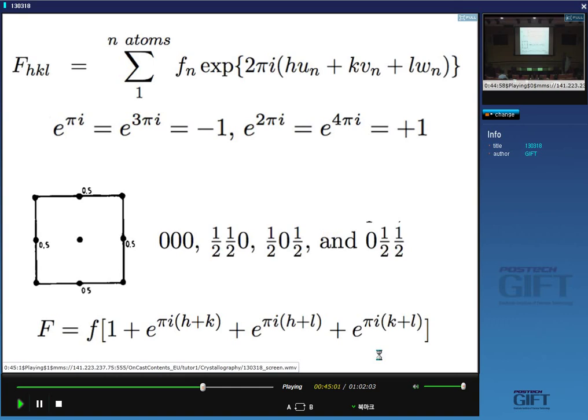So this is now the structure factor for our copper. And if I substitute any plane into this, then I will get whether we should get a reflection from that plane or not. So supposing I substitute HKL equals 1, 0, 0, then I have 1, this will be exponential pi i, because it's 1, 0, 0. This will be exponential pi i, and this will be exponential of 0. So what's the sum there? Well, it's 1, minus 1, minus 1, plus 1. So I do not get anything from the 1, 0, 0 planes. Yeah? Happy with that?